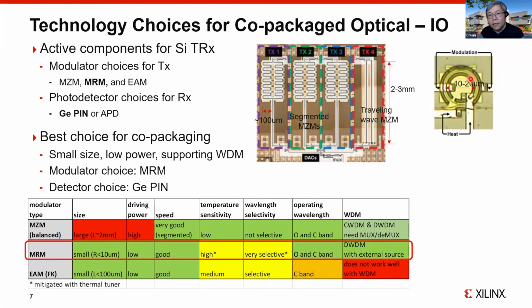Contrary to that, the micro-ring modulator is much more compact. For high-speed modulation, the ring radius is less than 10 microns for sure, closer to 5 microns. So the size of the modulator is 10 to 20 microns across. That provides a much more compact solution, and the power consumption needed to drive such a device is much smaller compared to the Mach-Zehnder modulators.